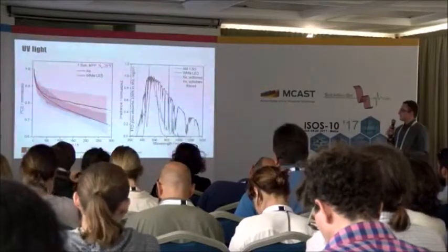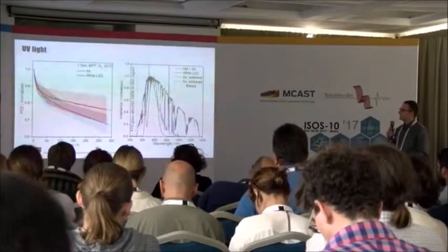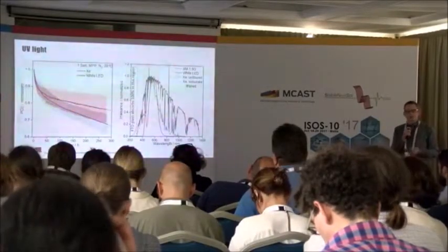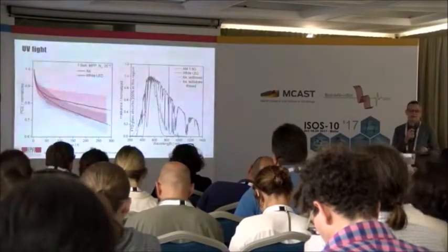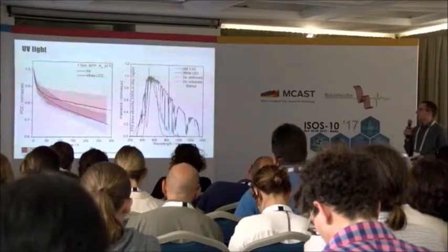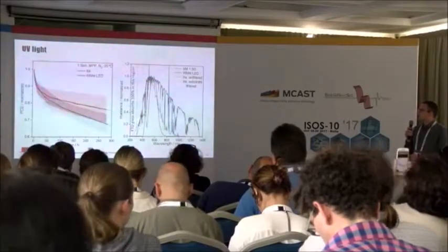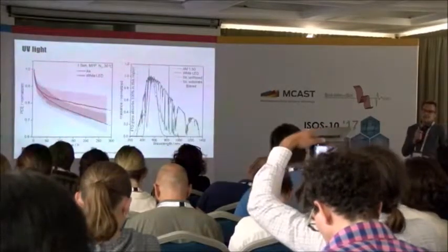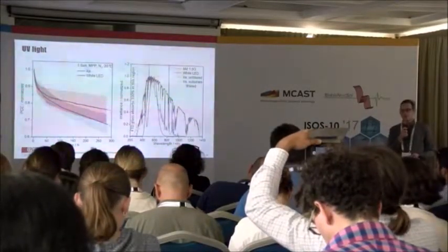When we use xenon lamp, the degradation is slightly accelerated, but the difference is not dramatic. It's not like what we've seen Henry showing, that the devices die within 5 hours. And the source of light was unfiltered xenon, so it has much more UV light than the solar spectrum.